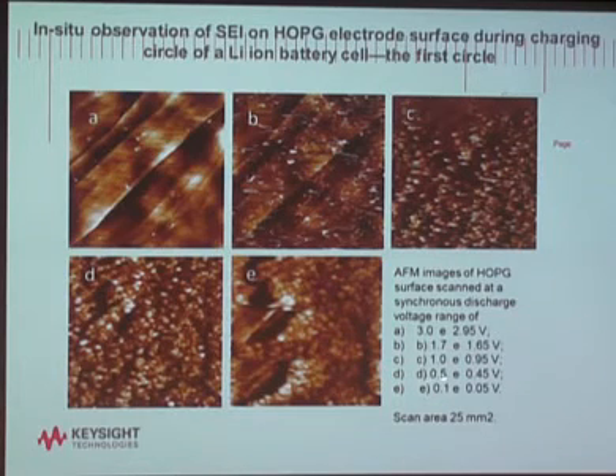At about 0.5 volts, something happened. From here to here, there's a lot of wild drifting in the system. We don't know what happened. Later on, we'll find out what happened. Here we see a formation of little clusters. And these clusters actually stick to the surface of the electrode. At a certain point, about 1 point some volts, right here, these formed this cluster. They form a crust. And at this point, the crust actually leaves the surface. They delaminate. That's what we saw.